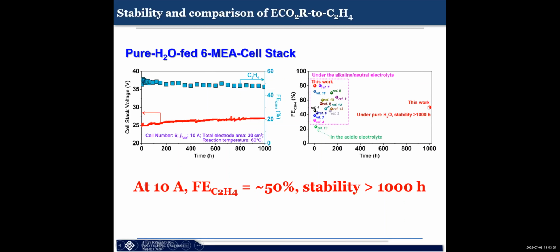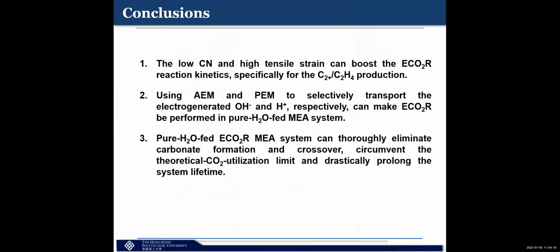If we use water, the Faraday efficiency is just in between the best and the not-so-bad ones. But we can extensively extend the stability, the lifetime. So in the long term, this process becomes much more practical, and if we just use pure water, it will simplify a lot of problems later on. Even the CO2 purity is not very critical if we use water, because it would not lead to other products. I think my time is almost up, so I'll just summarize.